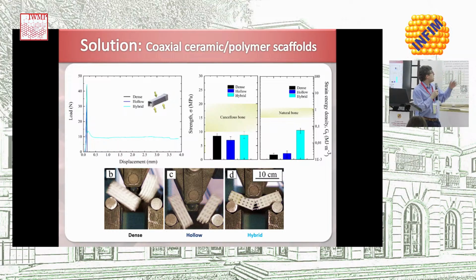And as you can see here, you see the typical brittle behavior that you see on the dense and hollow struts, this sudden drop, and as you can see, a catastrophic failure of the material in bending. They just pop out. You see them breaking in milliseconds, and that's it, they are gone. Your material is no longer useful for anything.